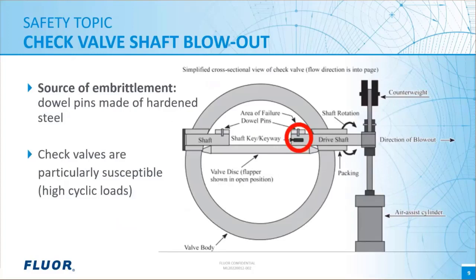So if we take a look at a cross-sectional view of this check valve, you can see in this red circle here, that was the location of failure, specifically in the dowel pins. The dowel pins are made out of hardened steel, which is more prone to embrittlement. And they're also used to retain the shaft within the check valve. And so when the pins failed, the shaft blew out. And this is what caused the leakage and explosion.